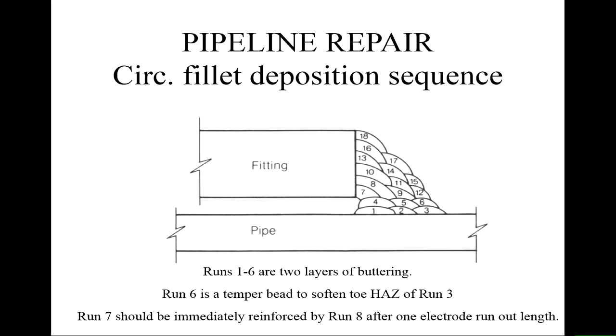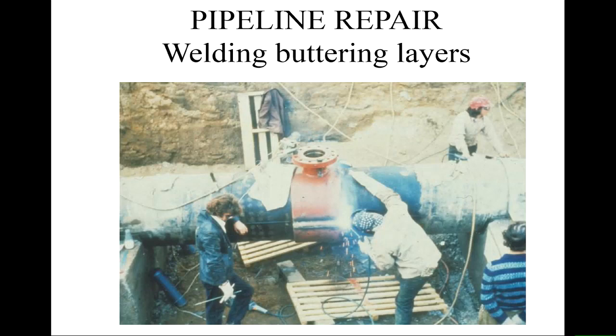Run 7 and run 8 need to be very quick, because otherwise you get contraction stresses setting up, and run 7 fails, cracks through, separates from the surfaces, and then you get poor performance. So they're the key passes. And you just want to make sure that those are done within a fixed amount of time. So this is welding those buttering layers on a different setup.